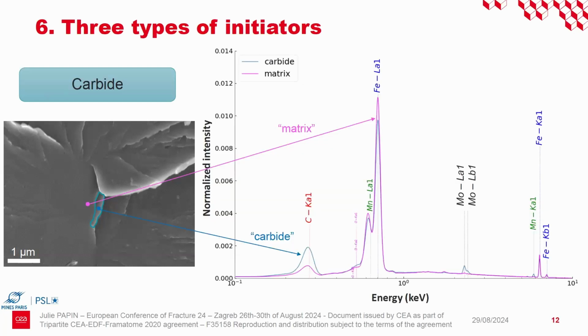The carbides can be identified in a scanning electron microscope using energy dispersive spectrometry. And here is a typical spectrum of carbides in blue, which defines the peak of higher enrichment of molybdenum compared to the matrix, and the higher peak of carbon, and less significant, but there is a higher peak of manganese too.